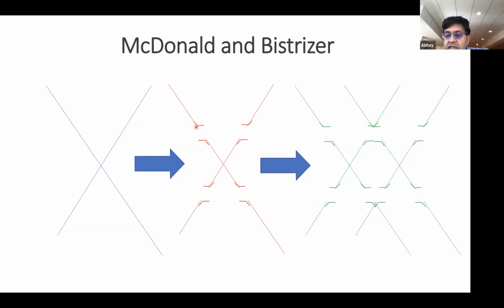Moiré superlattice. Now, something that Allan MacDonald and his student realized back in 2011 is if you have a real bilayer of graphene, I have 2 layers of graphene, in order to do the calculation properly, there are 2 effects going on. One effect is the fact that there is a superlattice, and the superlattice exists on each of the 2 layers. But the second effect is that electrons can hop back and forth between the 2 layers. And we all know how to handle that.